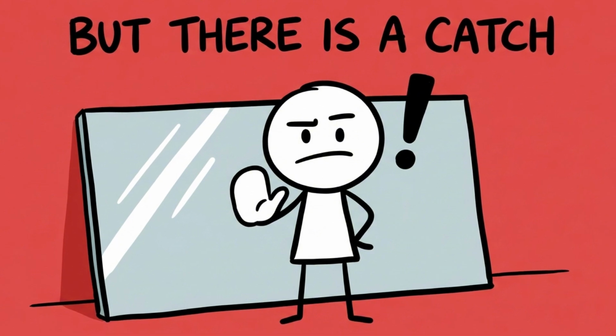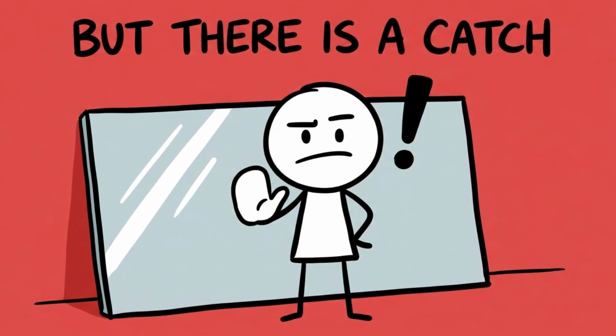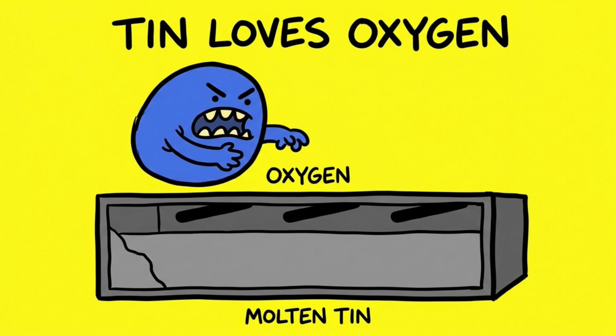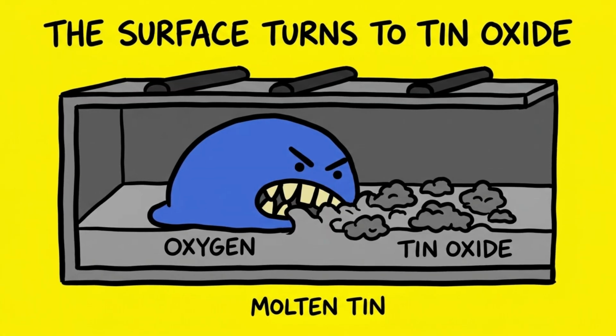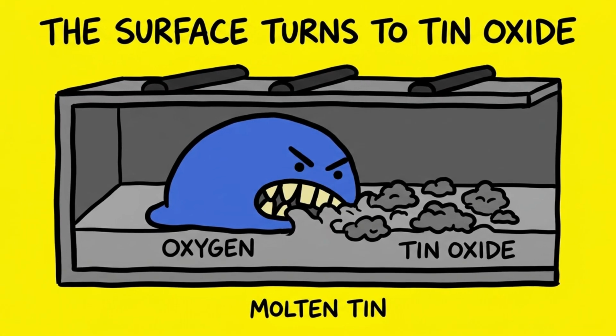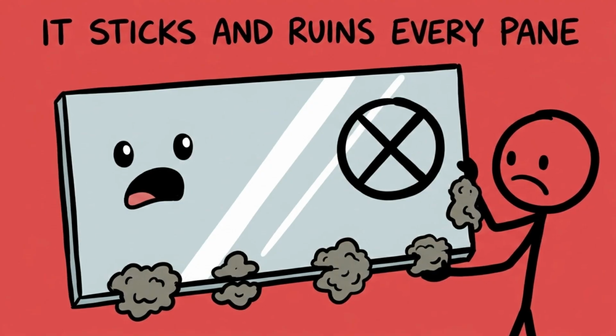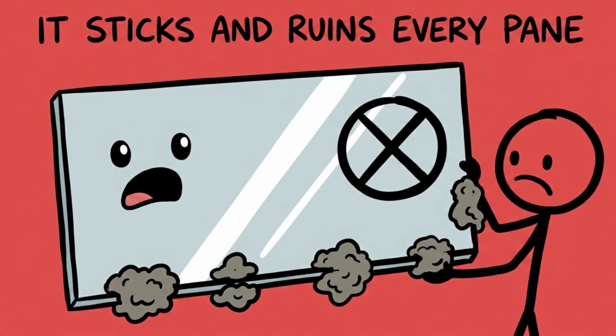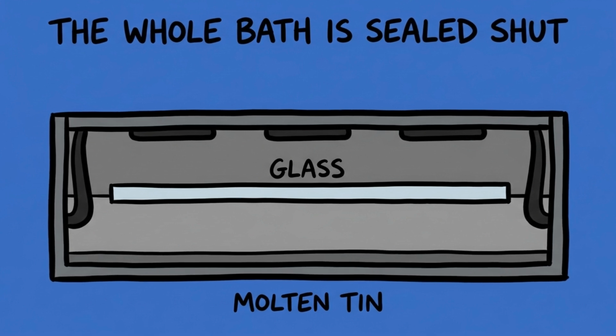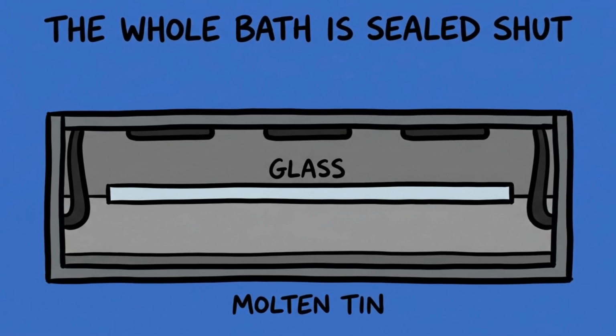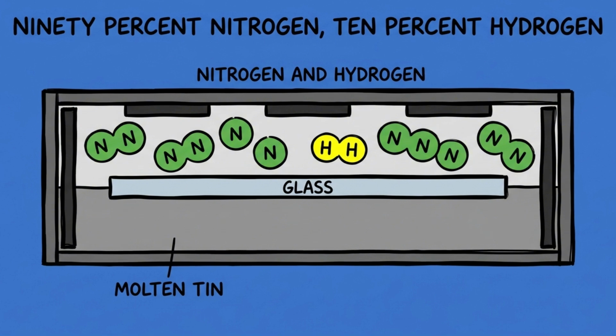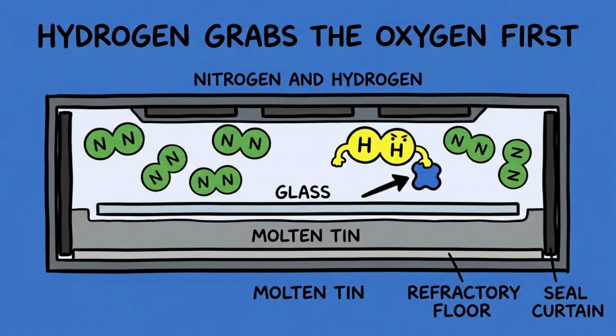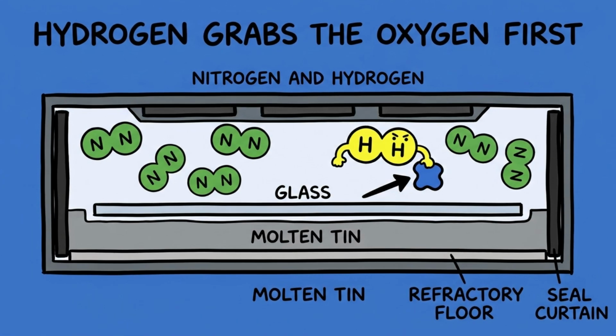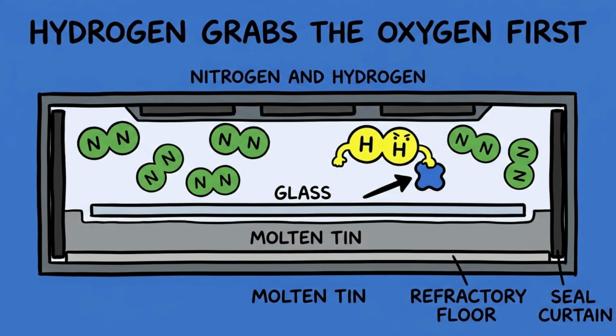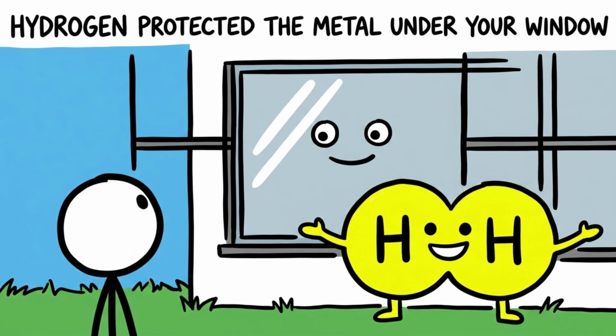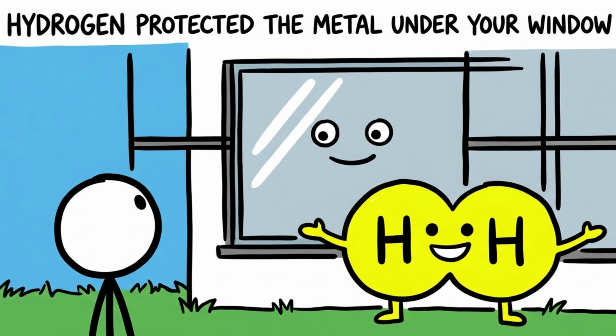There is a catch, and it is the reason this took 7 years. Tin loves oxygen. Open that bath to the air, and the surface turns to tin oxide, which sticks to the glass and ruins every pane coming through. So the whole tin bath sits sealed under a blanket of gas, roughly 90% nitrogen and 10% hydrogen. The hydrogen grabs any stray oxygen before the tin can reach it. Your window is flat because a hydrogen atmosphere was protecting the metal underneath it.